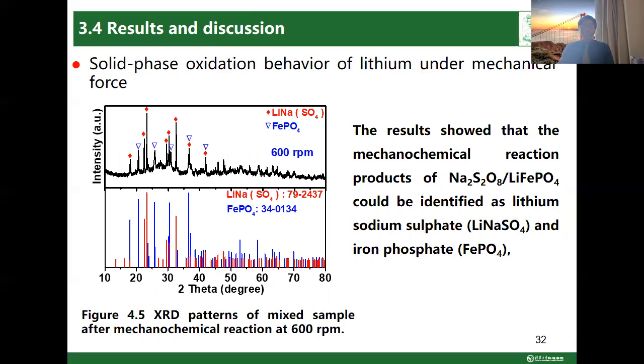Figure 4.5 also shows the XRD pattern of the material samples after the mechanochemical reaction at 600 RPM. The results show that the mechanochemical reaction products of the material could be identified as lithium sodium sulfate and iron phosphate, indicating that this material disappeared through mechanical force and was converted to another material.